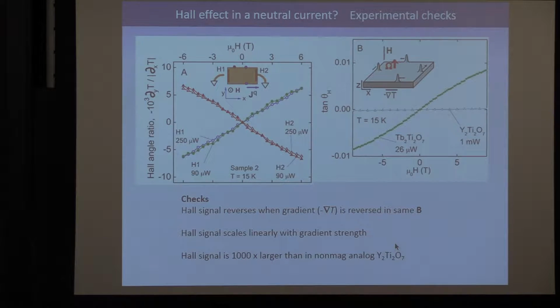So this is really a Hall signal. It changes sign with the direction of the current, as well as the field. Field you can change in situ, obviously. Right? So that passed the test. Moreover, it scales linearly with the heater power, right? So going from 90 to 250 microwatts, you see the same kappa XY. So you're measuring something real rather than a spurious effect.